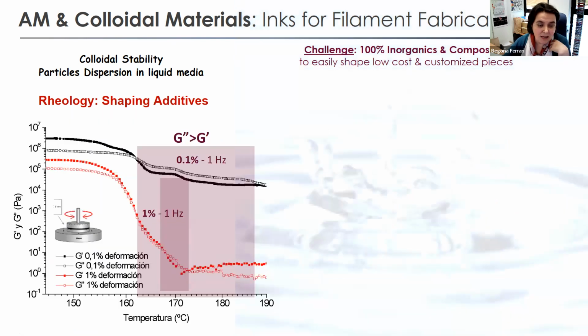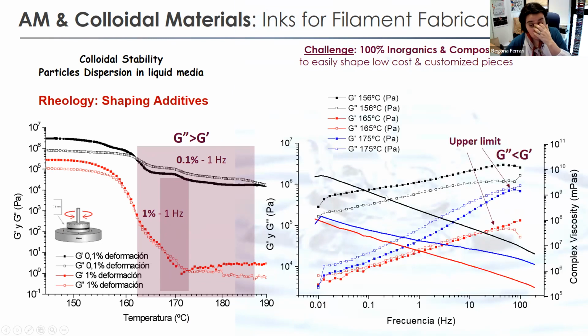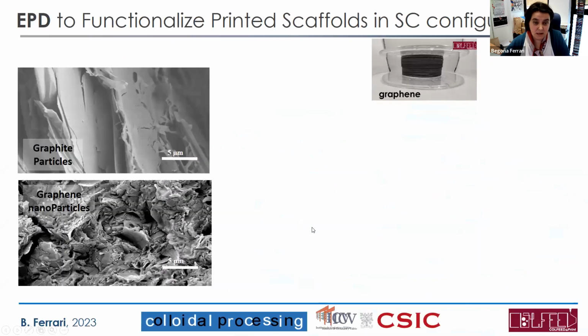It can also give us an idea of how we need to work, because if we change the deformation of this material, of course, the behavior changes. In this case, for low deformation, we have a viscoelastic material, but with higher deformation, most of the time we have a solid material, so we cannot print it. And finally, we can describe the rheology of this melt, which gives us an idea of how we can extrude and print our thermoplastic materials.